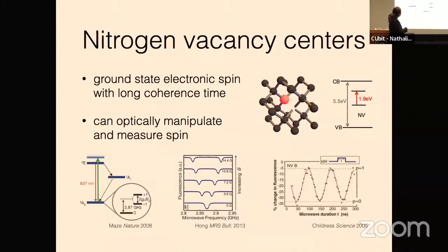But if I'm in plus or minus 1, I have this spin-dependent intersystem crossing to a dark state. And this thing lives about 10 times as long as my excited state lifetime, so it effectively changes the number of photons I can scatter off of this defect in a spin-dependent way. So you can use this to read out the spin state of the defect. You can do optically detected magnetic resonance. So here I'm changing the microwave frequency as I go over the zero field splitting. And you can see this little dip in the total number of counts. And you can do things like just read off the local magnetic field by looking at Zeeman splitting.